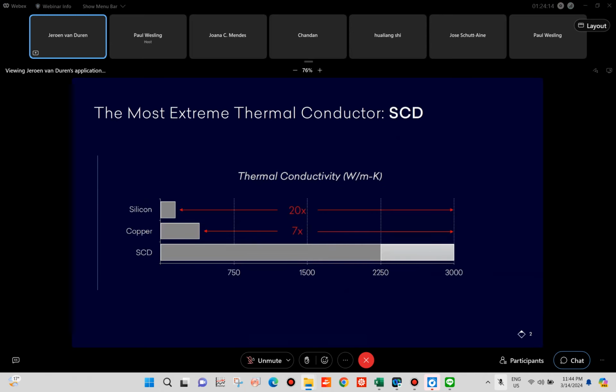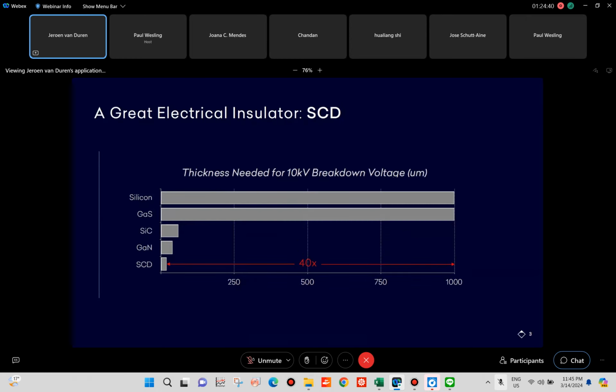As Joanna explained, diamond has a very high thermal conductivity. Our standard product is 2,200 watts per meter Kelvin. We even make 3,000 watts per meter Kelvin. And as you can see, that thermal conductivity at room temperature is up to 20 times higher than that of silicon and like 7 times higher than that of copper. So that's very substantial. And for heat spreading, that has a huge impact.